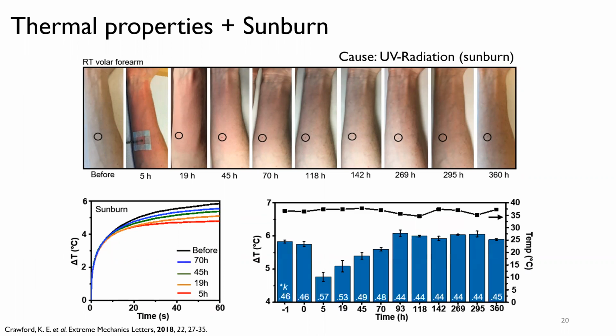This bar graph on the right is the same thing from the plot, but it's taken at the 60-second marks and then transposed into a bar chart. When we were collaborating with the clinicians, despite our year to year and a half of very hard work figuring out that this thermal conductivity is 0.46 watts per meter Kelvin or 0.57 watts per meter Kelvin, the clinicians were really just interested in seeing this visual change of how the sunburn is healing as a function of time.